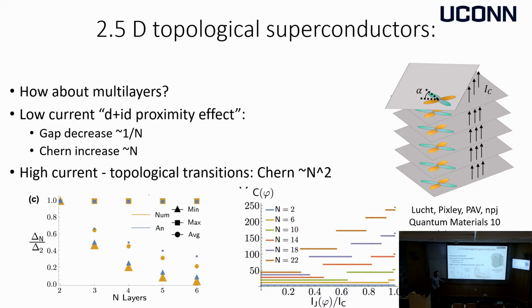And one of the really crazy results is that if you do the same thing I told you about, applying a current going through the stack, we see topological transitions. This is Chern number. This is current in units of critical current. And as you add more and more layers, so for a few layers, as you go up to critical current, the Chern number is the same. But if you go to more and more layers, there are these transitions, jumps in the Chern number. And at least mathematically, if you believe this model, you can show that you can get up to Chern number of order n squared. So you have n layers and n squared edge modes.